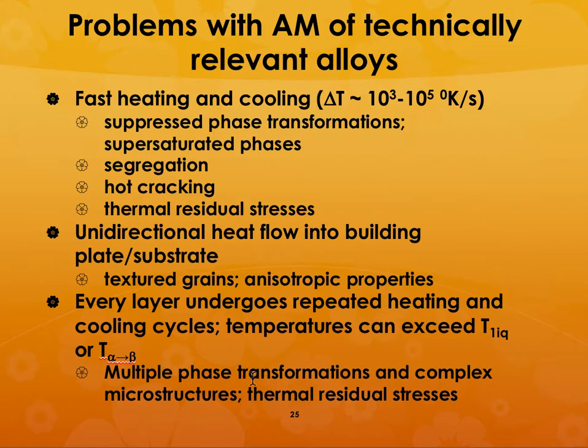And after you build one layer, it is going to go down and then you are going to be building another layer on top of that. So even though that layer may not go to the same temperature as the layer being melted and joined, it is still going to be undergoing repeated heating and cooling cycles. And in this case, if there are going to be phase transformations taking place, those temperatures can exceed the liquidus temperature, and some phase transformations, etc.